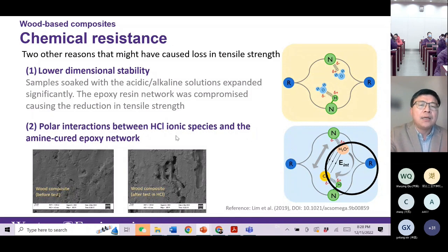Another mechanism is about the internal tension. For the original materials, epoxy resin and wood, after curing, we add some amine to cure that. This amine can repulse each other. They create some internal strain, internal tension inside. But if this material is in contact with the HCl, the hydrogen chloride, they create some electrostatic force within the materials. They have an attraction force. This attraction force balances some tension, so the overall tension reduces.